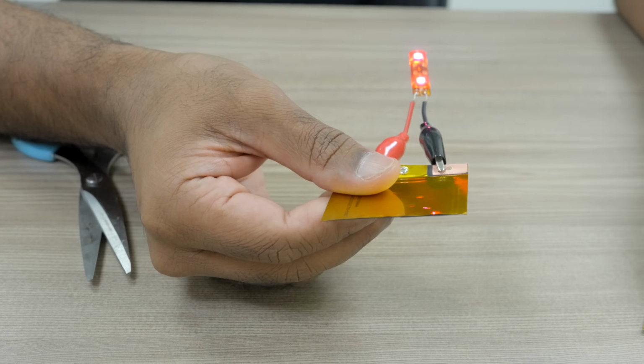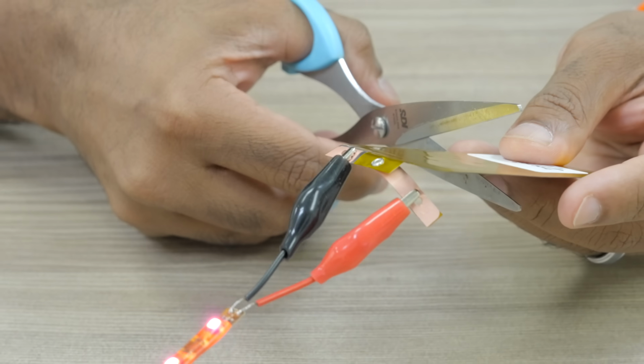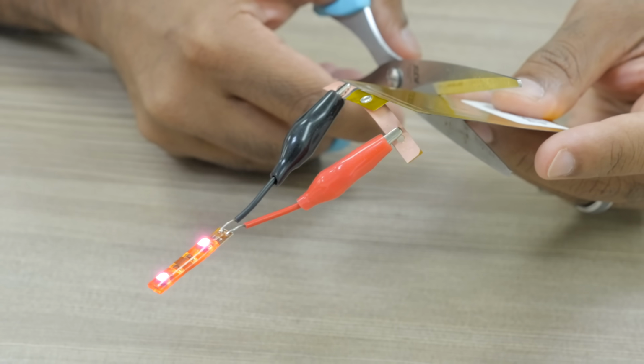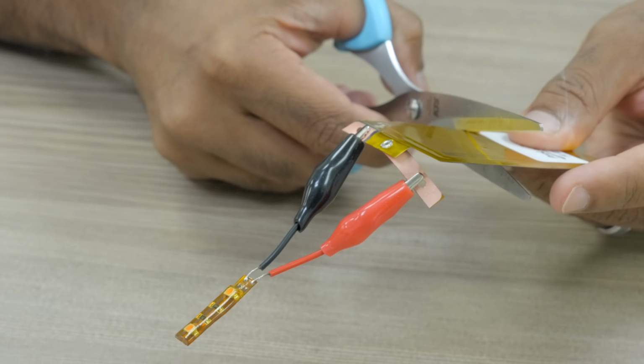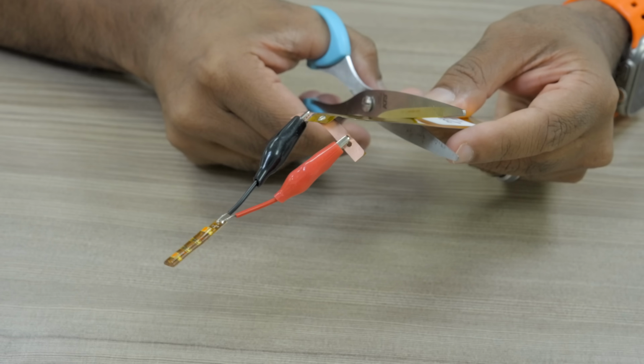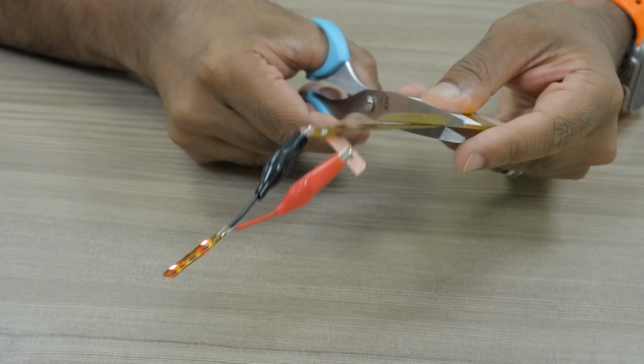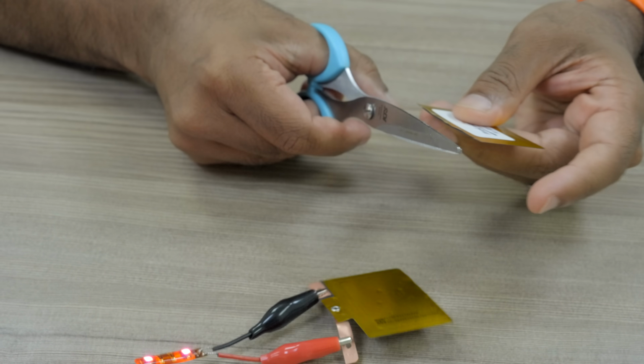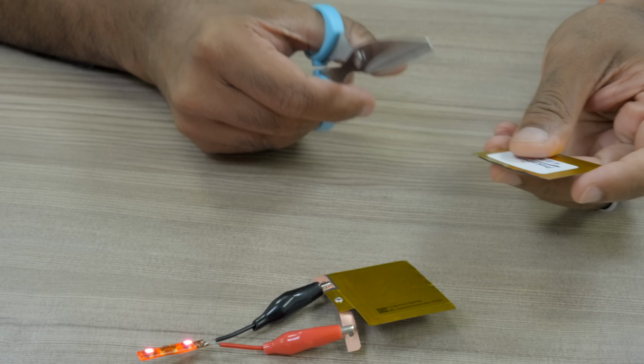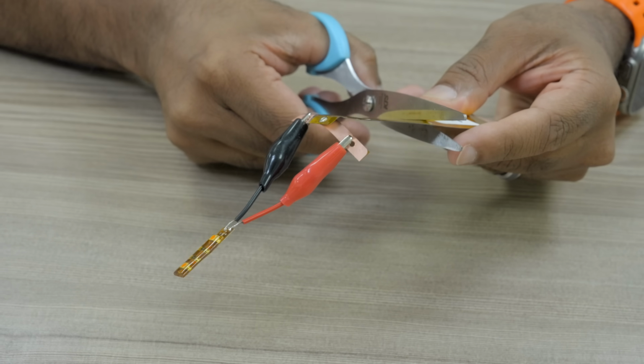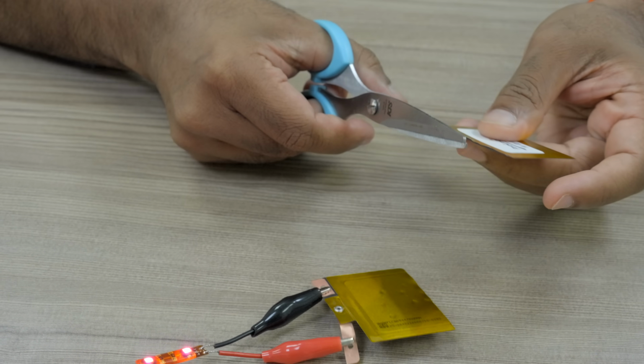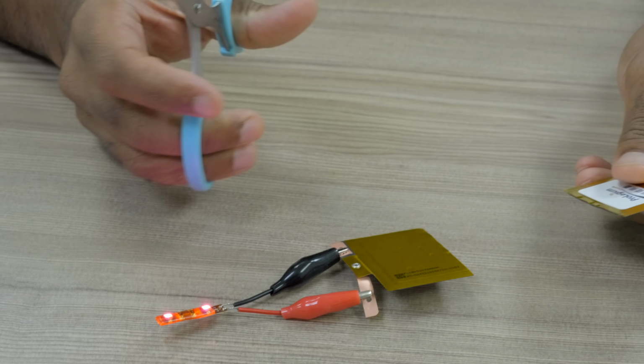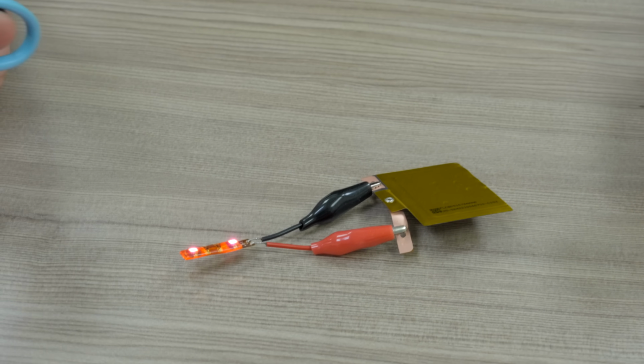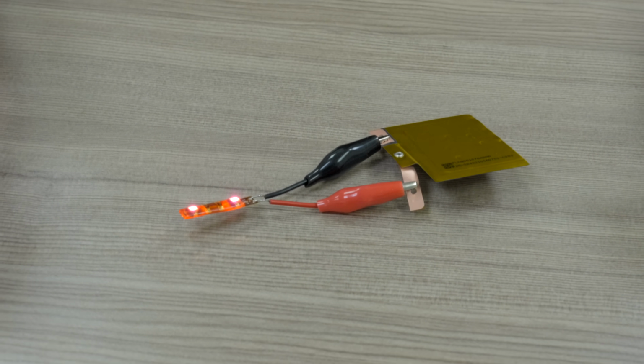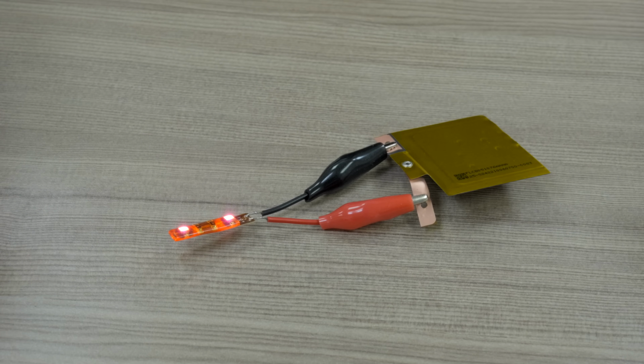Very interestingly, if we slow this down, you can see that the LED goes out when the metal in the scissors shorts the two electrodes, resulting in a voltage potential between the two dropping to zero. But once I finish the cut and the scissors are removed, the short is removed, and the cell recovers and the light comes back on. That's a clean cut through both current collectors, anode, cathode, and separator. And other than losing half its capacity, the cell kept on going. And most importantly, nothing leaked.